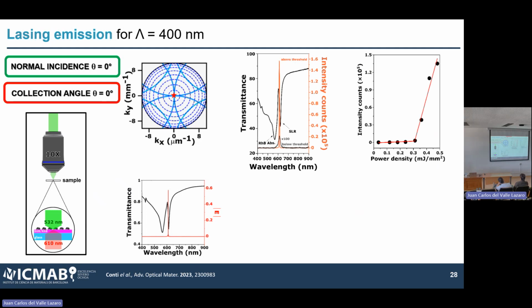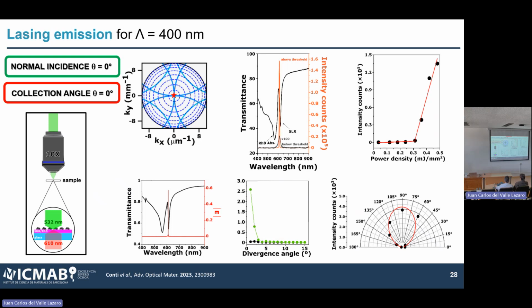So basically, we confirmed it by analyzing the emission, because there are other processes that can explain this very sharp emission. To make sure that it was lasing, we first of all looked for a threshold behavior, and then we looked at the divergence. If it is lasing, it should be, as you can see here, 1 or 2 degrees in distribution. So if I move the detector away from the sweet spot, I should stop seeing lasing, as you can see here. And then finally, we look at the polarization of the generated light. The prediction is the red one, and our data are the black spots.